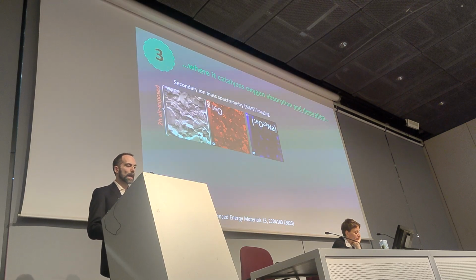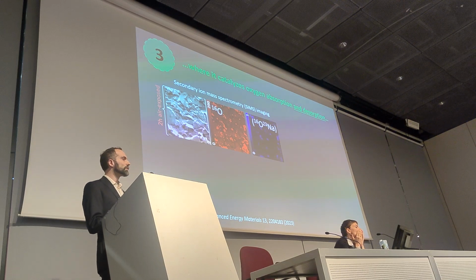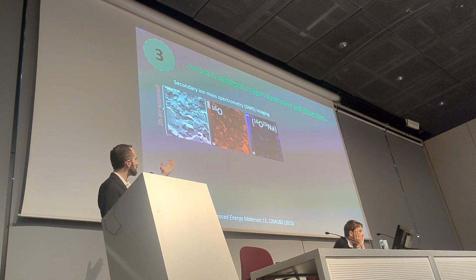Given this, what does the sodium do at such interfaces, at grain boundaries? Well, this is a spoiler. There it catalyzes oxygen absorption and also desorption. As we have seen from secondary ion mass spectrometry imaging, we have performed this experiment that clearly demonstrates that oxygen is not just physisorbed, but it is chemisorbed and it is associated with sodium.